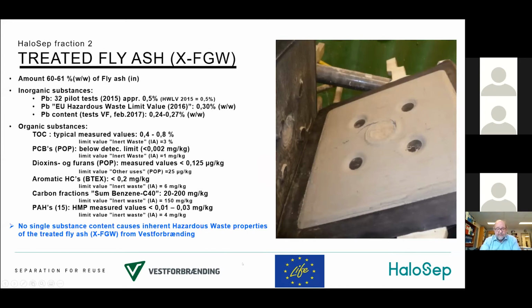And speaking about technical challenges through the development of this process, in 2015, we had about 0.5% of lead in the treated material. And the hazardous waste limit values, according to the CLP regulation, was 0.5%, so we were close to the limit. And then the EU changed this limit value to 0.3% in 2016. So we had to go back and do some pilot testing in order to meet this demand. So in 2017, we have routinely about 0.24 to 0.27% lead in the treated material.